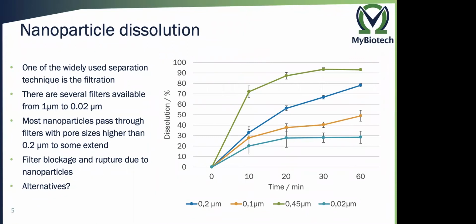Just to give you an example of how it normally would look like if you use the syringe filters, which is mostly used for the conventional dissolution studies. So if you have microparticular API, which is not dissolved in the dissolution medium, you take your sample, you filtrate it through a syringe filter, and on the other side of the syringe filter in the filtrate, you have a clear solution without any microparticles. The issue with the nanoparticles is they go through these filters. From, let's say, 1 micrometer down to 0.2 micrometers, you don't have any chance that these nanoparticles will be filtered, or most of the nanoparticles will not be filtered. They will just go through the filter and you have nanoparticles in your sample.